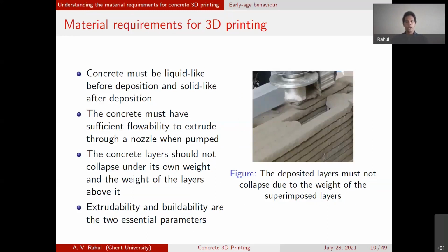So an order of magnitude higher than what you would have with conventional concrete. But because its yield stress is so high, when it's exited from the pipe, it's able to retain its shape. To make this high yield stress material pump, we use specially designed pumps that are able to pump this high yield stress fluid. And then once it's deposited, once it's free of stress, it's able to retain its shape. That is the idea that we utilize in concrete 3D printing, to design it for very high yield stress.